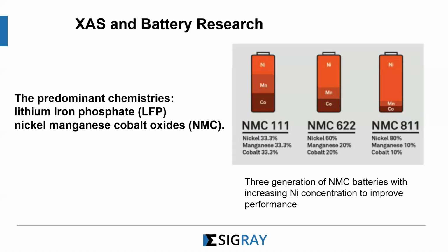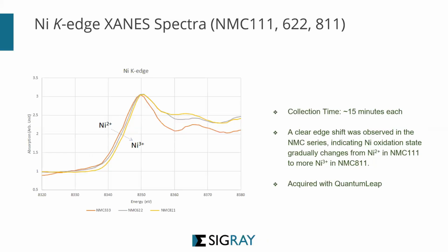The next generation is that they'll try to reduce the cobalt and the manganese and increase the nickel. So they came up with a combination called 622 with 60% nickel, 20% manganese, and 20% cobalt. And the 811 is 80, 10, and 10. So these are the three generations of NMC battery with increasing nickel concentration. So we did a run to show that, okay, if you run all these three, you find that there is a shift in the oxidation state from your 111 to your 811, where you see the nickel is shifting towards the right because the oxidation state has increased.